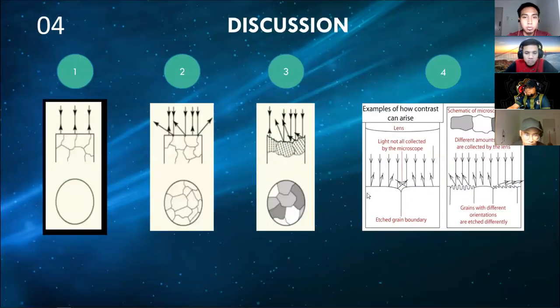And for the discussion, the first image shows a specimen with a polished but unetched surface. This provides a clear image for the microscope but excludes information about the specimen microstructure. And then the second is this specimen etched with grains having the same orientation. And then the third picture shows an etched surface with differently oriented grains. And lastly it illustrates how contrast can be created by an etched surface which includes an etched grain boundary. And then next.